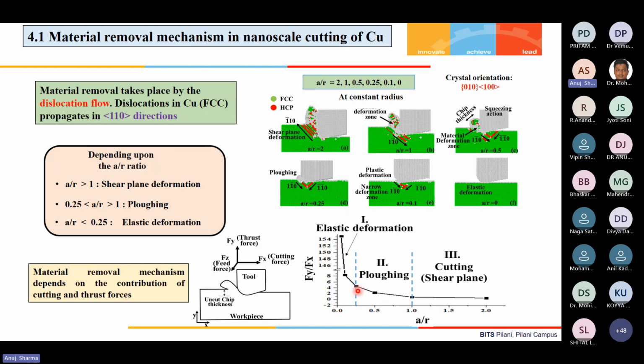Based on these force ratios, we can define those 3 cutting regions in this cutting simulation. For A/R greater than 1, there is shear plane deformation. That means through shear action, cutting or chip formation is happening. For A/R ratios from 0.25 to 1, the plowing mechanism takes place. Plowing means the material is going sidewise, an extrusion-like phenomenon. Half of the material is going ahead of the rake face of the tool, and some amount of the material is going beneath the tool. And for A/R less than 0.25, only elastic deformation takes place.